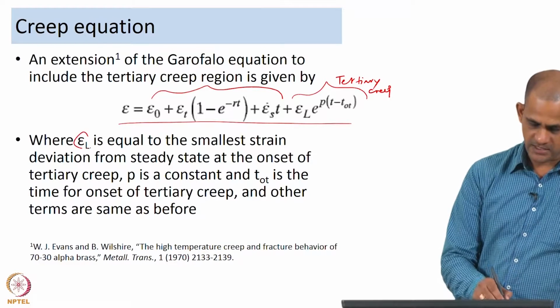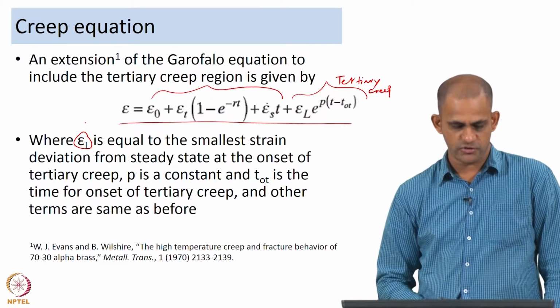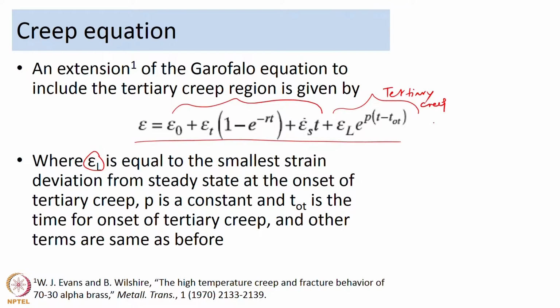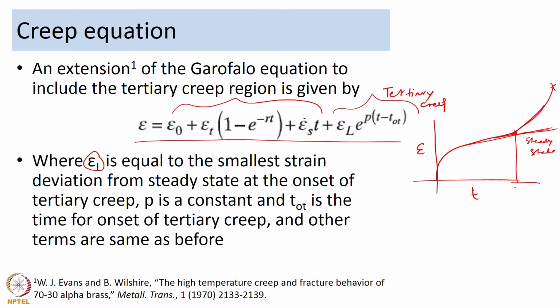Here epsilon L, which is the new term that they introduced, is equal to the smallest strain deviation from the steady state at the onset of tertiary creep. So, if you look at the curve epsilon versus t, it is the smallest strain that takes the material away from steady state. If this is the extrapolation of steady state, the smallest strain deviation which takes the material away from steady state into tertiary creep, that is what epsilon L is, and p is a constant and TOT is the time for onset of tertiary creep. So, probably somewhere around here this will be TOT, and the other terms are the same as before.